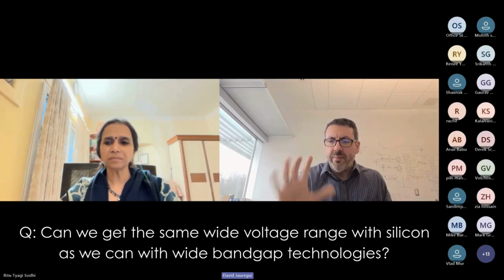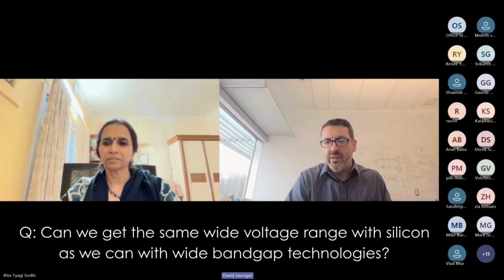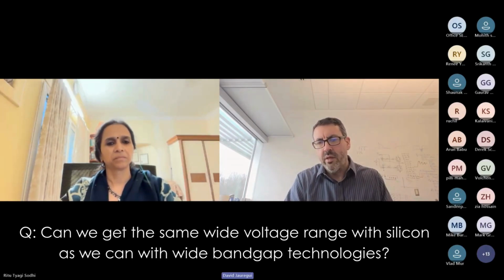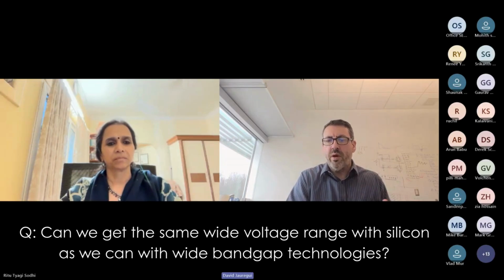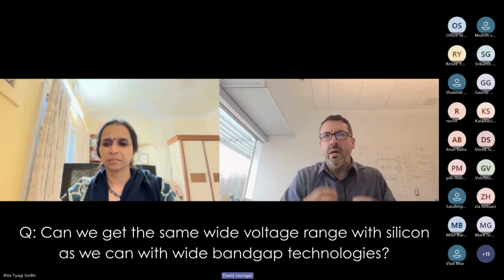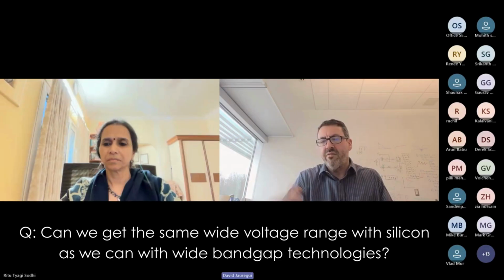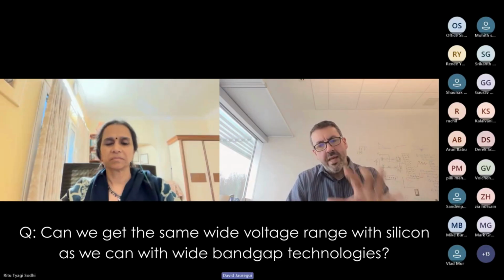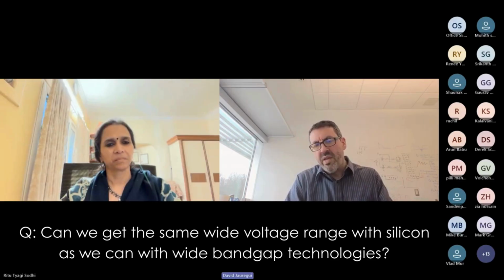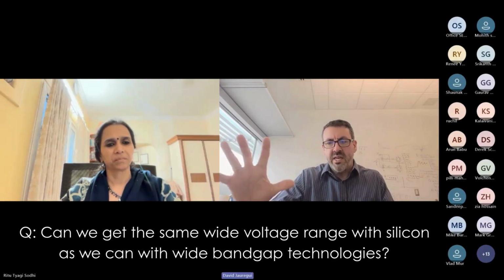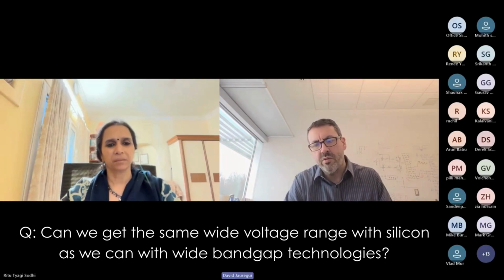And so if you need to have an application where you have to run at 200 degrees C, then you've got to use silicon carbide. So what you try to do is make products with the value proposition that is needed for the application. High electric field is one parameter, but you've got to know where to use it. And I think at 10 kV, absolutely, silicon carbide should be the leader there.